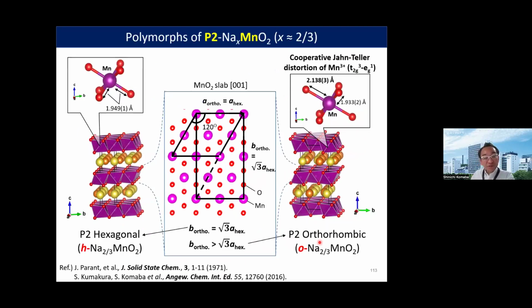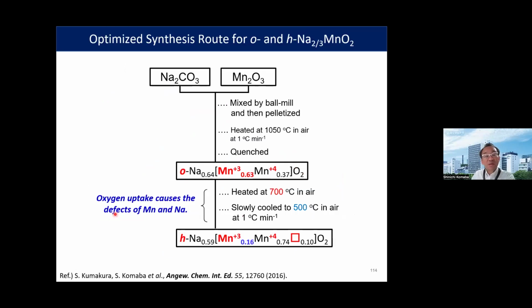So the next one is manganese layered oxide. Because of Jahn-Teller distortion, some previous reports show a rhombic, that is distorted, structure named orthorhombic P2-type sodium 2/3 manganese oxide. On the other hand, some previous reports show no Jahn-Teller distortion, and then a hexagonal P2-type structure can be found. Always these two phases are mixed, but there is almost no report of pure phase synthesis. So we tried to make pure orthorhombic and hexagonal sodium manganese layered oxide.